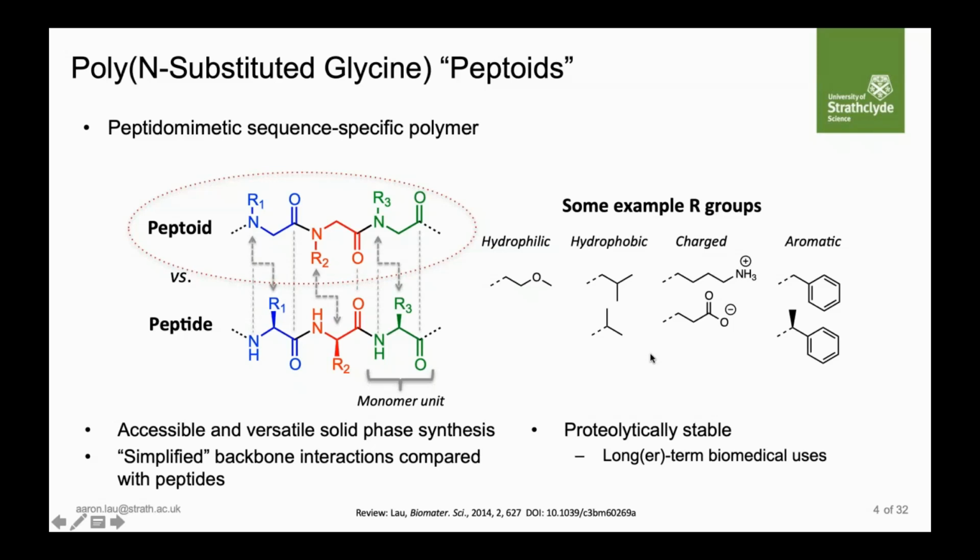So here I'm showing the schematic for an alpha peptoid, and showing how the difference with the alpha peptide is simply a 1 atom position shift of the side chain. Of course, that changes chemistry, which we'll come to, but also it's taking out the hydrogens along the backbone. And so it really, in a way, simplifies the hydrogen bonding of the system, and it's a bit more modular. You focus on the side chain functionality to try to achieve both structure and function.